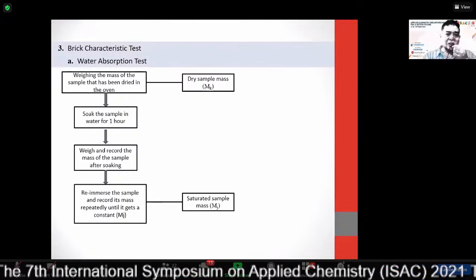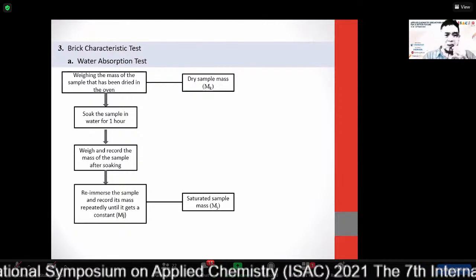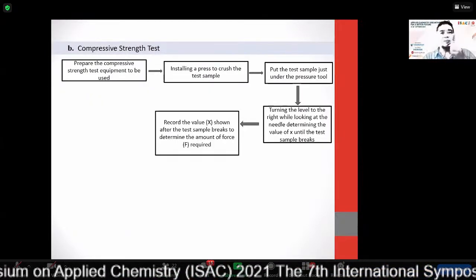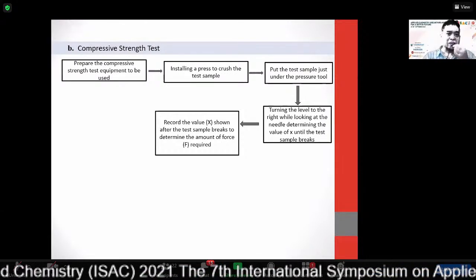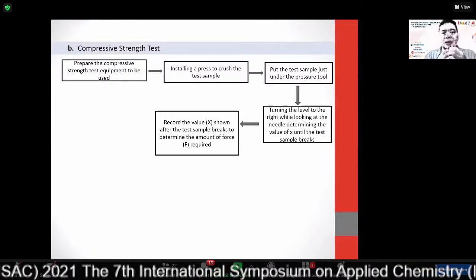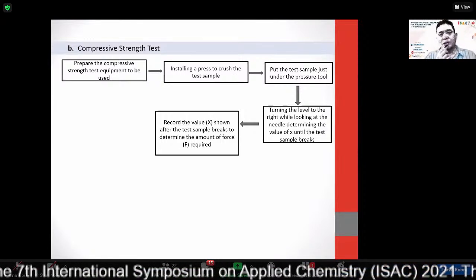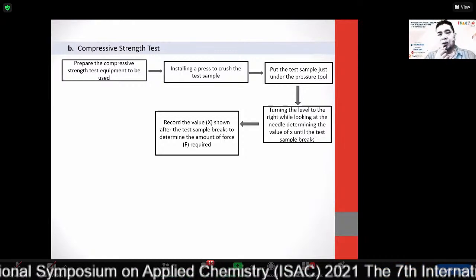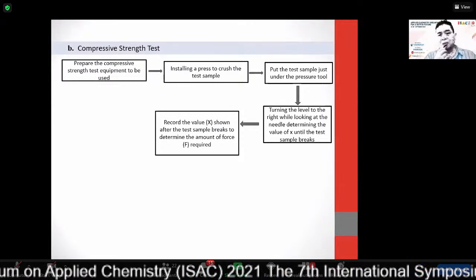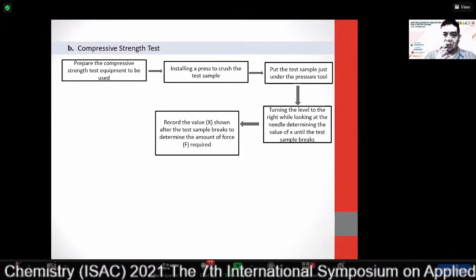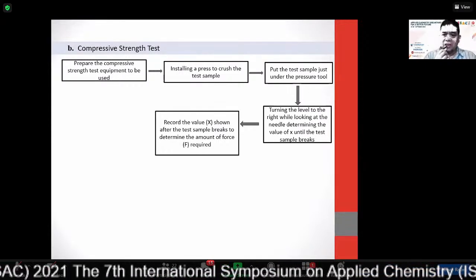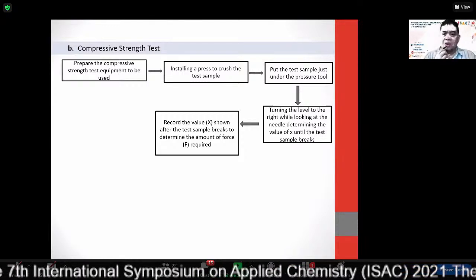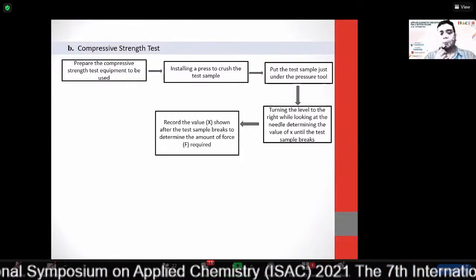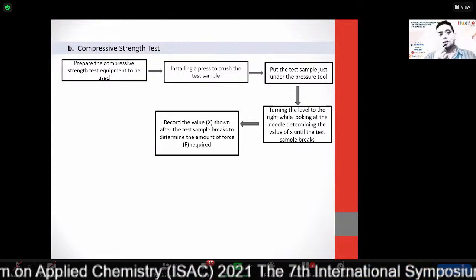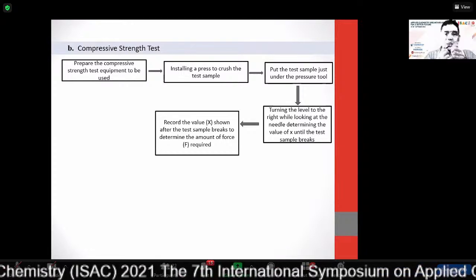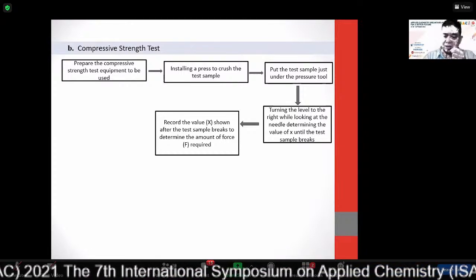Water absorption test, using like this, and then the compressive strength test. Prepare the compressive strength test equipment to be used, install the press to crush the test sample, put the test sample just under the pressure tool, tune the level to the right while looking at the needle, determining the value of X until the test sample breaks. Then record the value of X after the test sample breaks to determine the amount of force that is required.